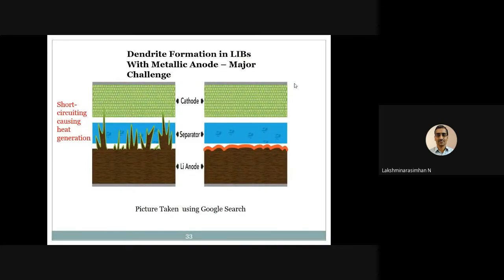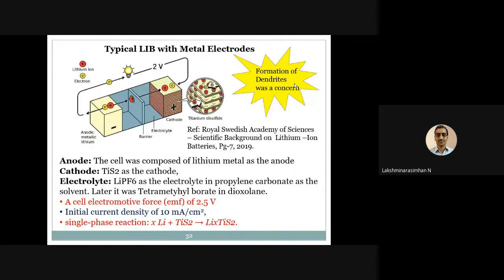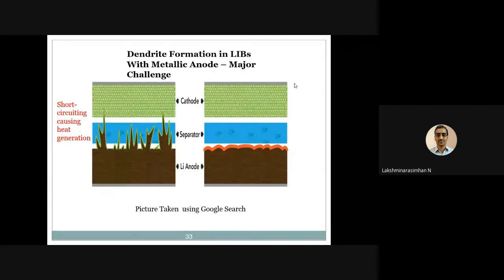The issue was this. Suppose you have an anode material made of metallic lithium. If the anode was made of metallic lithium, suddenly after a few cycles of operation, some dendritic structures grew, like in caves, because of the calcium deposits, it grows, right? Similar to that, some deposits grew inside the battery. It was so sharp that it penetrated, it grew and grew and grew. It penetrated the separator, which avoids direct contact of anode and cathode. Now it is broken because of these sharp structures, and it started touching. Then the whole short circuiting happened internally. Like external short circuiting, this is called internal short circuiting, and sudden explosion or sudden firing happens.